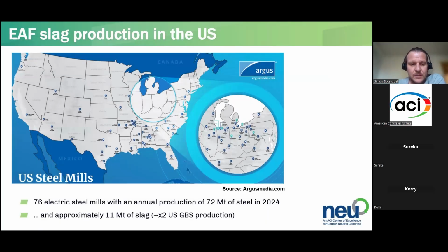If we have a look at the US, there are about 70 to 80 electric steel mills, with an annual production of some 72 megatons of steel. If we do a quick calculation of about 15% slag rate, which varies a bit, it could be 10, could be 20, we would get approximately 11 megatons of slag in the US today, which equals about twice the production of blast furnace slags in the US today. So again, this is a huge volume stream that could very well be utilized as SCM.